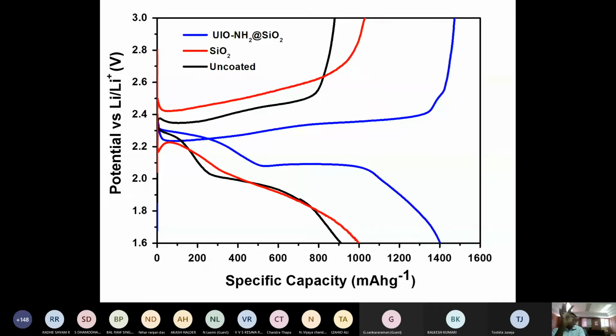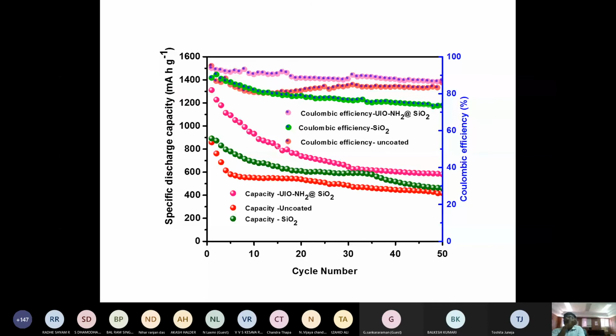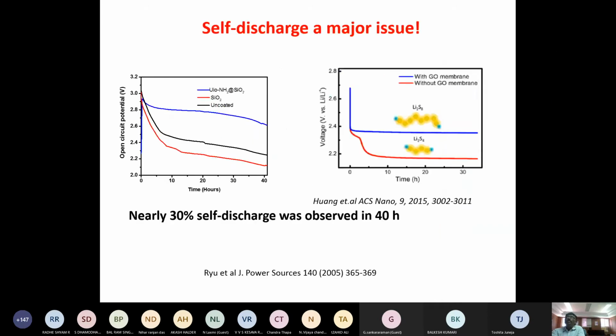And when we used it as a separator for lithium sulfur batteries, we were able to get 1400 milliampere hour per gram when we charge and discharge. Whereas the black one, which is uncoated, was able to deliver only 900 milliampere hour per gram when we charge and discharge our lithium sulfur batteries. And we have gone up to 50 cycles, and only the UiO coated one exhibited higher discharge capacity than the uncoated and SiO2 coated membranes.